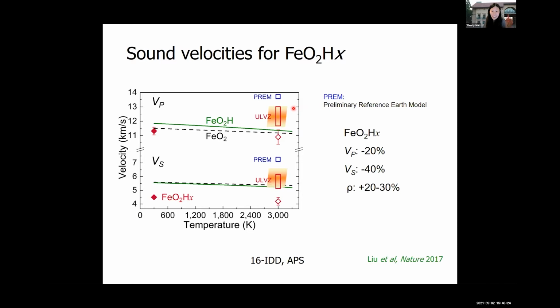So what about FeO2? Well, in order to even see if it's in the realm of possibility, we need to know the velocity and density of this phase. So Jin also determined the density and the sound velocities for FeO2H and FeO2 using X-ray diffraction coupled with another synchrotron technique, nuclear resonance inelastic X-ray scattering, which Jennifer Jackson discussed in her talk. And what we found was that compared to PREM, the compressional wave velocity is about 20% lower, the shear wave velocity is about 40% lower, and the density is about 20 to 30% higher.